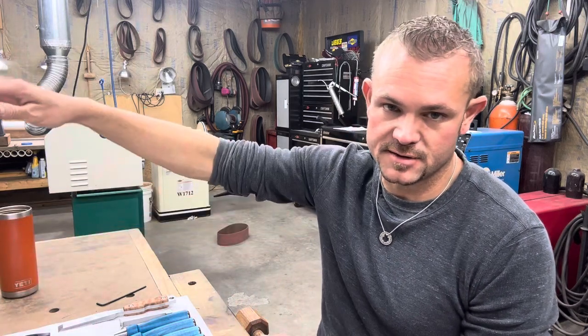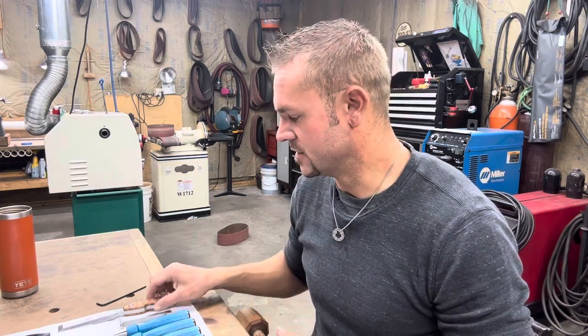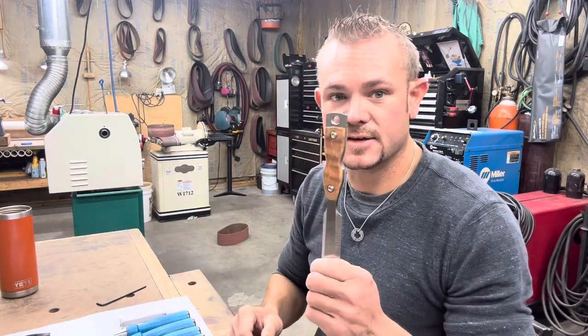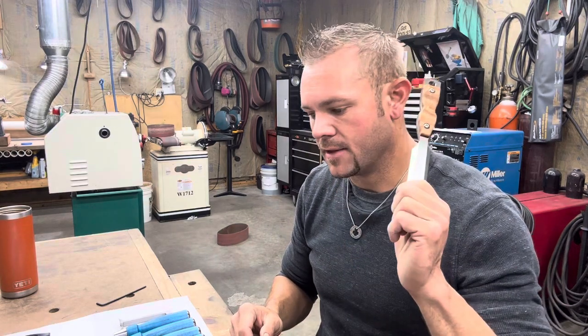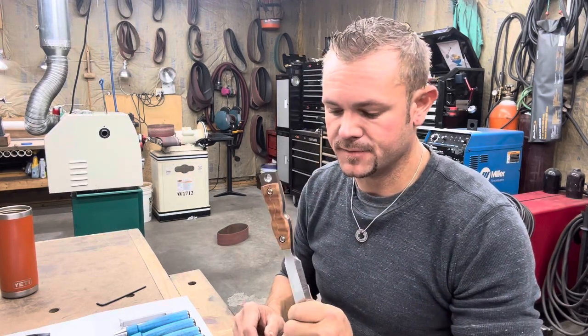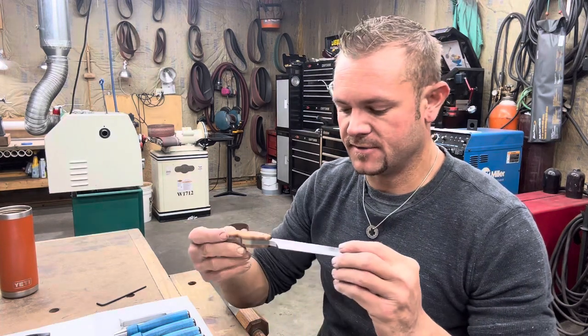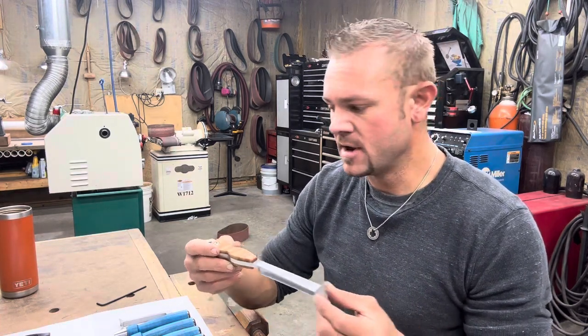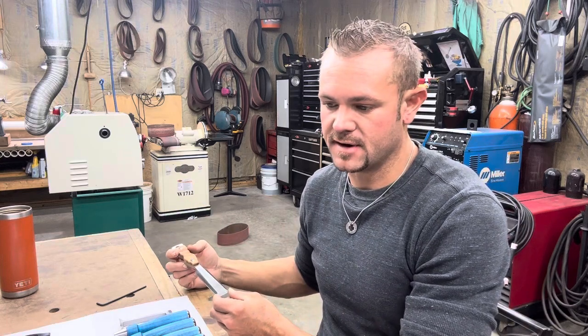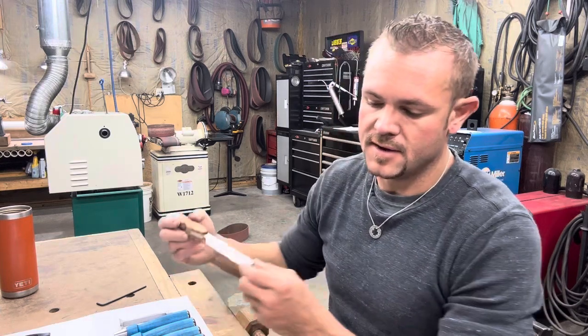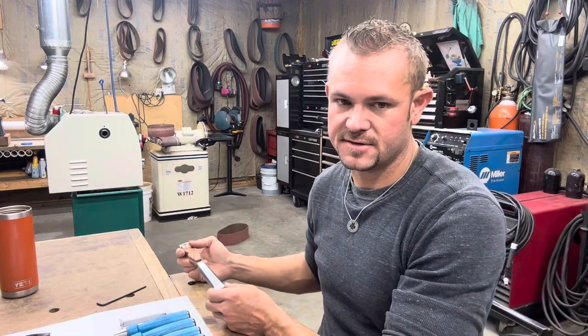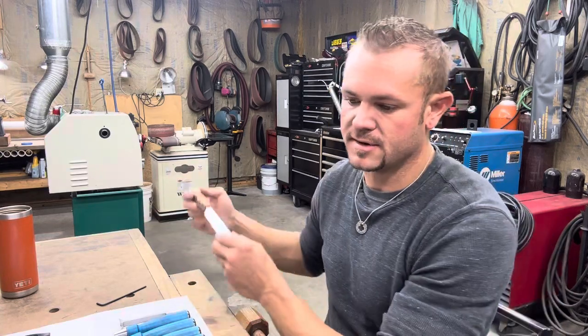And then it comes out of cryo and slowly comes up to room temperature, and then you go into the tempering temperature and slowly raise it up to the tempering temperature. And then you hold that there for X amount of time. For example, tempering Magna Cut takes 6 hours. 3 2-hour cycles. So this blade, after cryo, after all that stuff, was tempered for 2 hours and then allowed to rest in still air until it was room temperature. And then tempered for 2 hours and then allowed to rest in still air. And then tempered for 2 hours and then allowed to rest in still air.